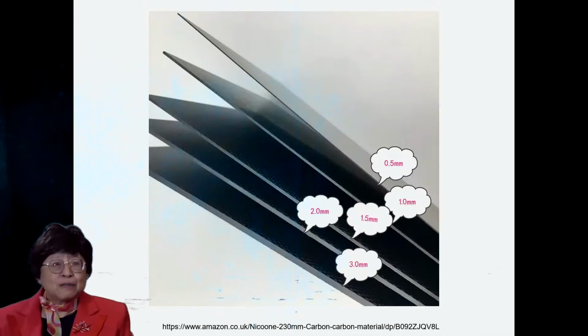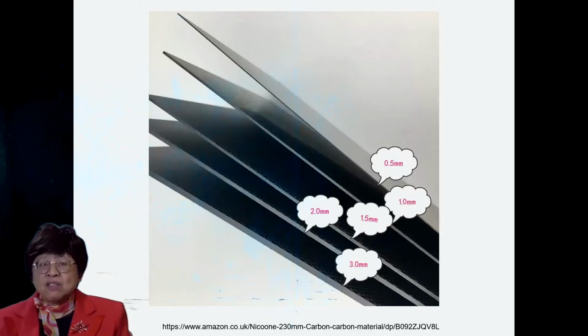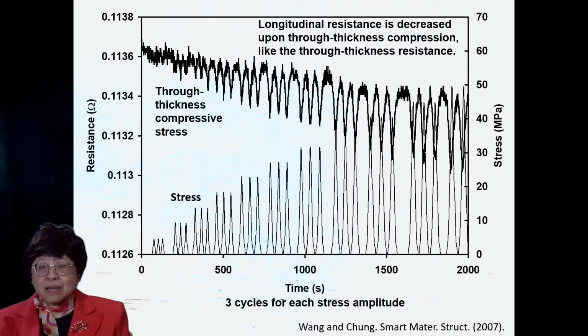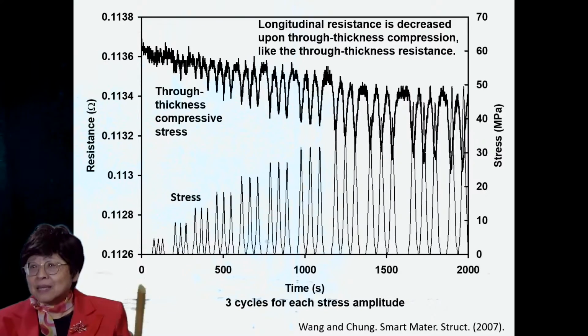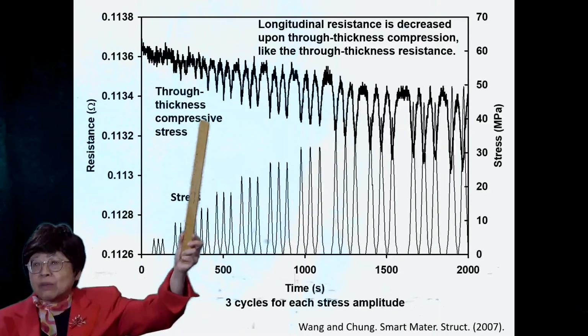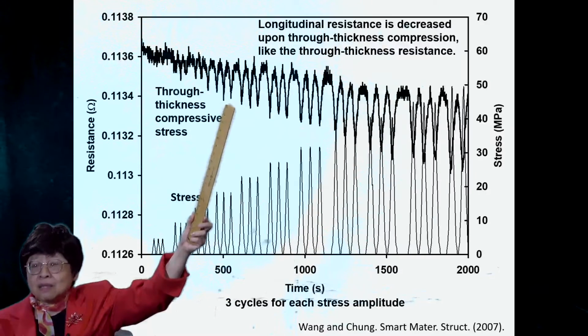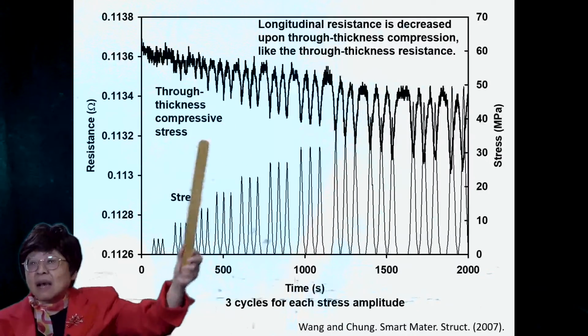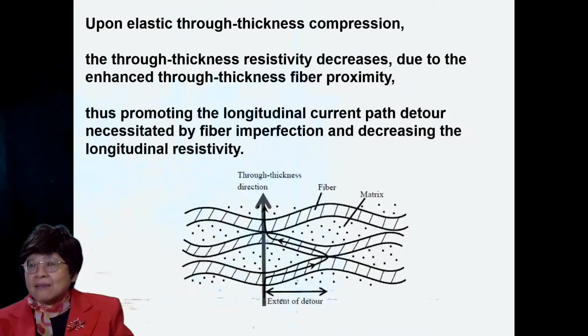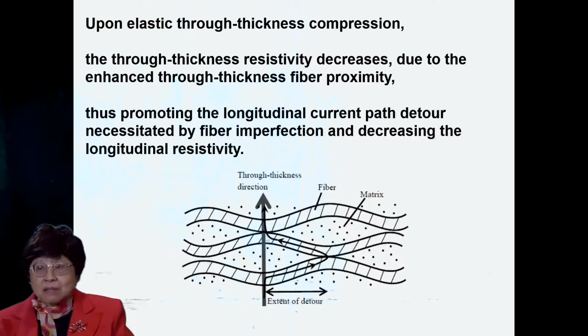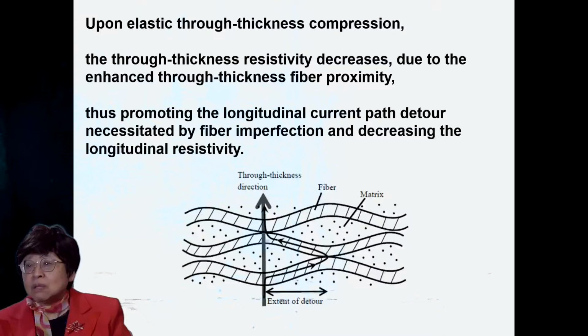Composite panels tend to be relatively thin, so measuring the through-thickness resistance is not so convenient. Measuring the in-plane resistance is much more convenient. We can actually measure the in-plane or longitudinal resistance in place of the through-thickness resistance and get similar effects. And this is again that squeezing in the through-thickness direction, and the longitudinal resistance, just like the through-thickness resistance, decreases every time one squeezes. And that is because the through-thickness resistivity decreases due to the enhanced through-thickness fiber proximity, thus promoting the longitudinal current path detour necessitated by the imperfection and thus decreasing the longitudinal resistivity.